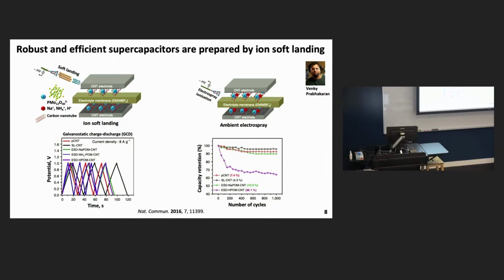On the right-hand side, we have the cycling stability of these devices. And you can see basically as you charge and discharge it, species prepared conventional ways show a substantial decrease in their charge retention, right? So we're about 30% reduction there. Whereas those prepared by ion soft landing retain almost 90% of their charge storage capacity, which is a clear advantage for energy storage.